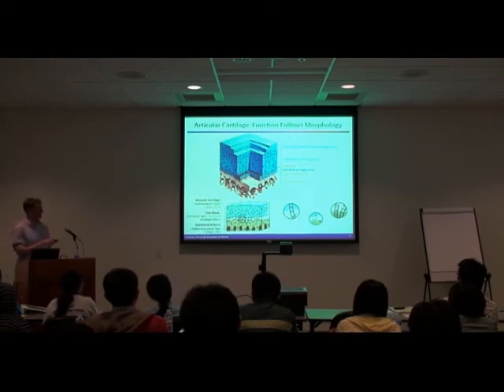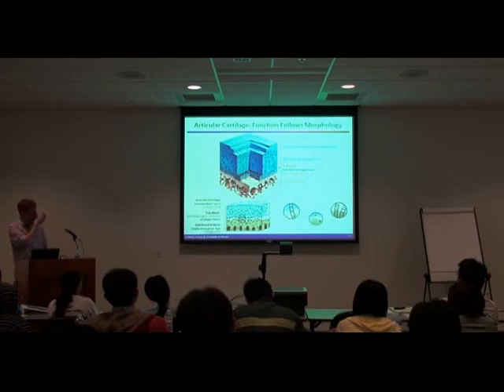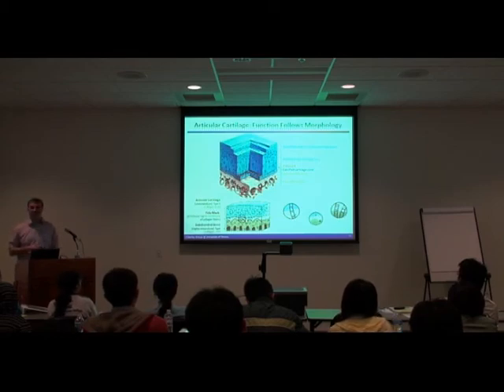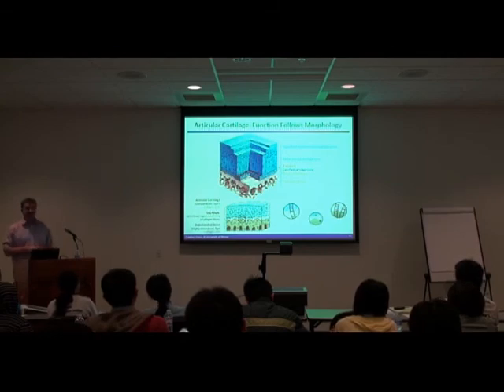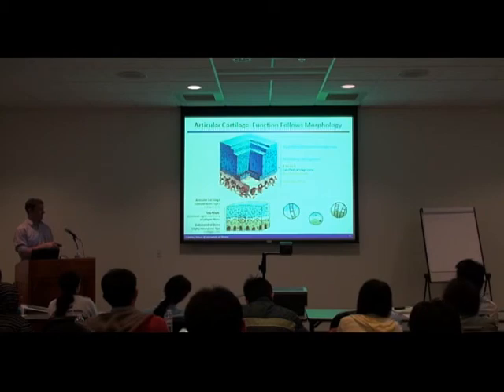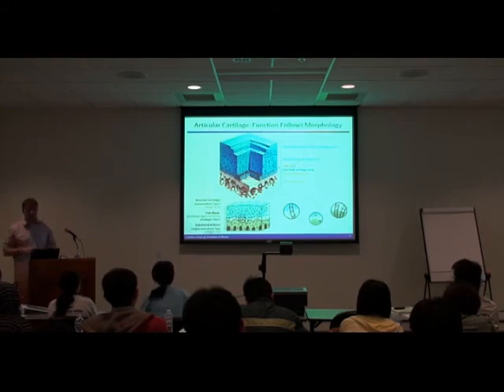There's nothing that really forces the surrounding cartilage to grow into the new material because it's such a low mitotic material. But the interesting thing from the biomaterials design is how osteochondral tissues are developed in the body. You don't have cartilage sitting on top of bone with a nice hard interface in between. What you actually see is you have your articular cartilage region, then you have this tide mark region, which has a gradual transition from non-mineralized type 2 collagen to mineralized type 1 collagen bone over this interfacial region and a continuity of fibers across it.